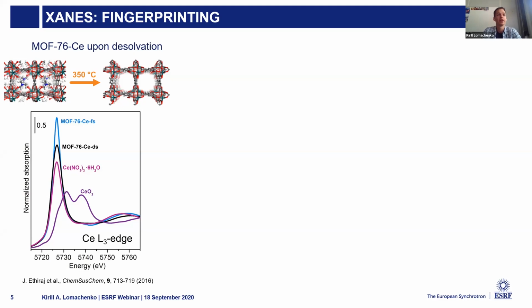To answer this very common chemical question, we have to measure two reference spectra of cerium-3 and cerium-4 compounds, cerium oxide and cerium nitrate, and then measure the spectra of our metal organic framework in fully solvated and desolvated states.